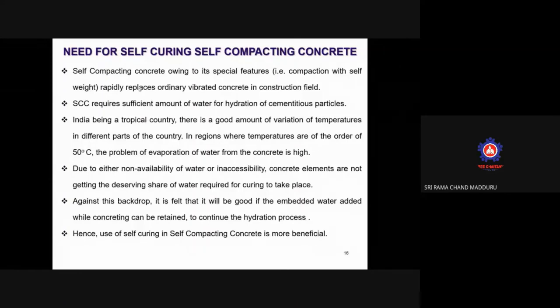If you want to hydrate all the cement particles, you need to decrease the evaporation of water. India is a tropical country where temperatures are typically in the range of 50 degrees centigrade in summer, so a lot of evaporation happens from the surfaces of concrete. Due to either non-availability of water or inaccessibility, concrete elements are not getting the deserving share of water required for curing to take place.